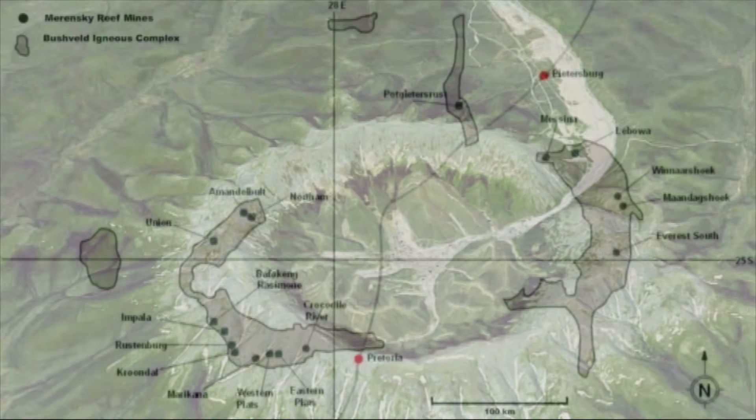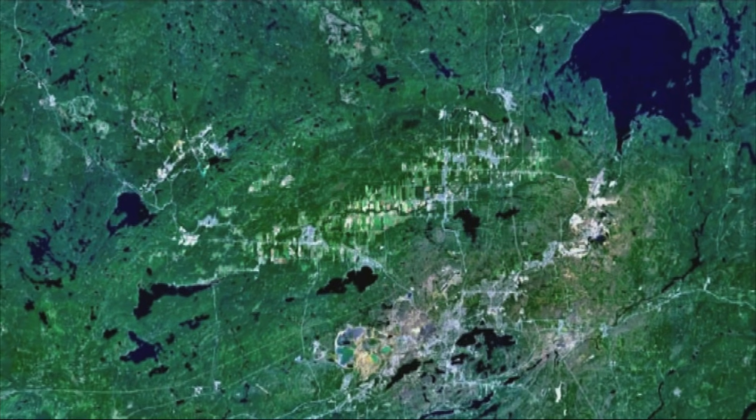It's important to stress that in the mines for the platinum group metals — the main mines are in South Africa, Russia, some in Zimbabwe, and some in Canada — the amount of platinum group metals in the rock is very, very small. To make an ounce of this sponge, you require somewhere between 10 and 40 tons of rock. The processing is also not instantaneous: once you've got the rocks out, to get the platinum material takes about six weeks of processing, letting things settle and processing some more. And rhodium takes another 14 weeks — so perhaps 20 weeks, nearly half a year — to get the rhodium from the rock to this stage. But once it gets here, they can process things really quite quickly.